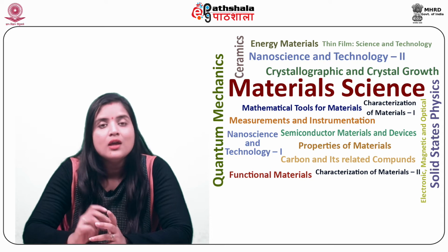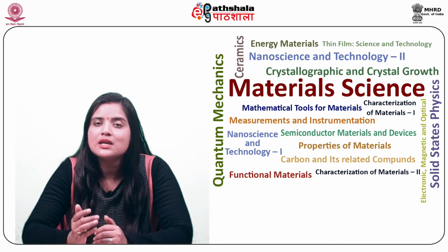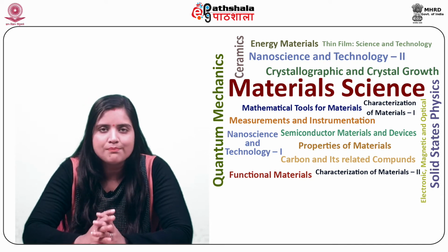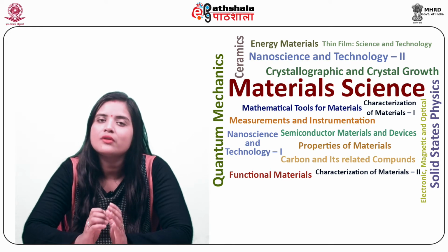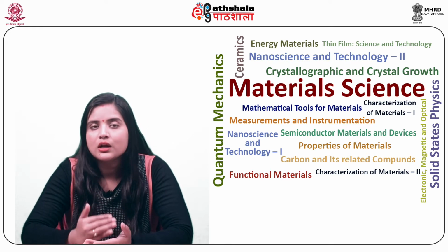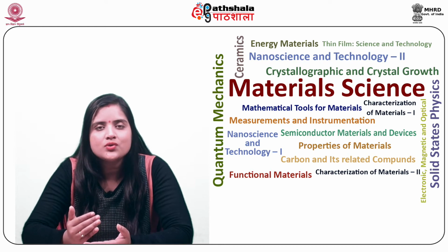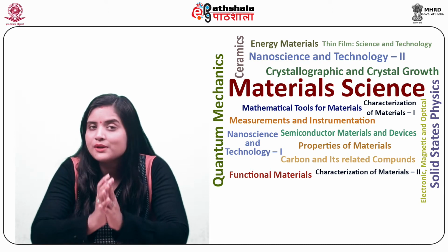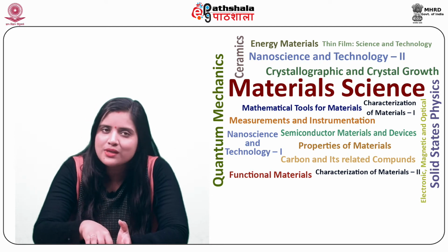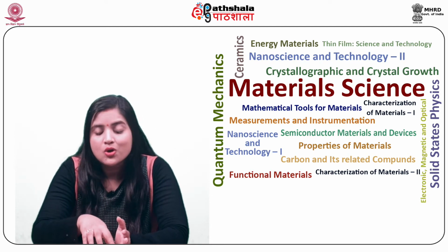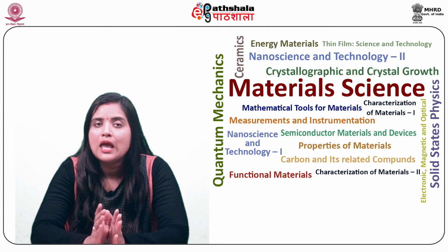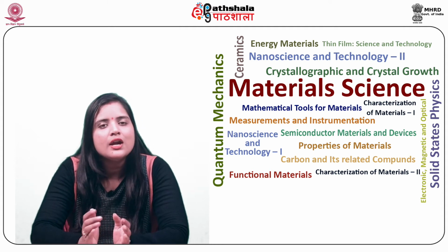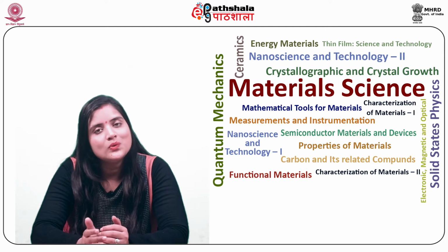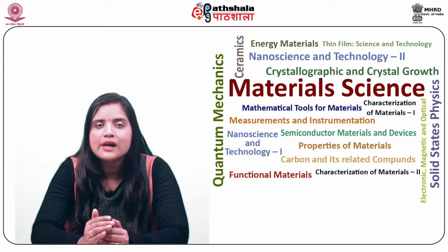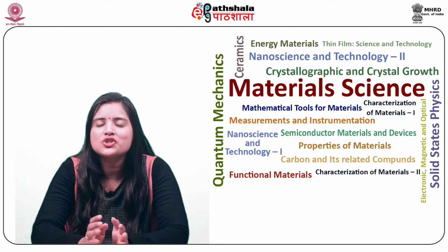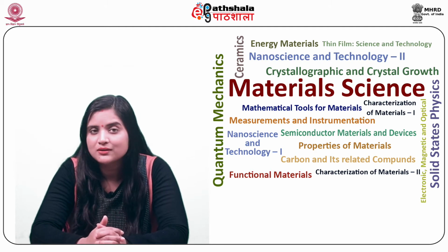Four-probe method equally applies to single crystal or bulk samples and can determine their resistances. Current flows through outer contacts near the sample edges and the potential difference is gauged across the inner contacts. Hence, the effect of interfacial resistance between electrodes and sample is eliminated by using this method.